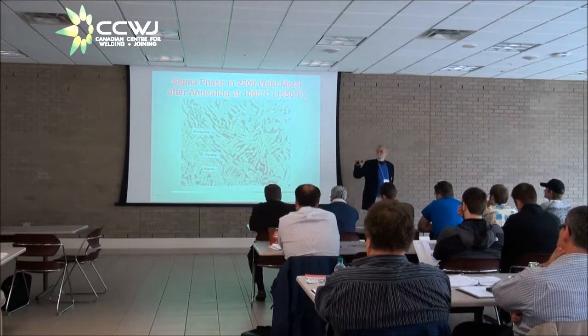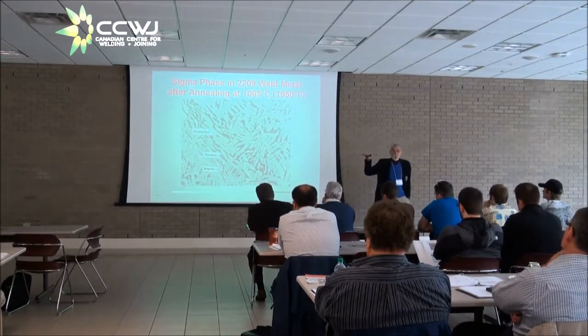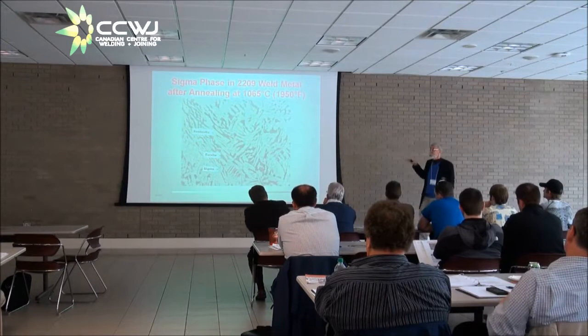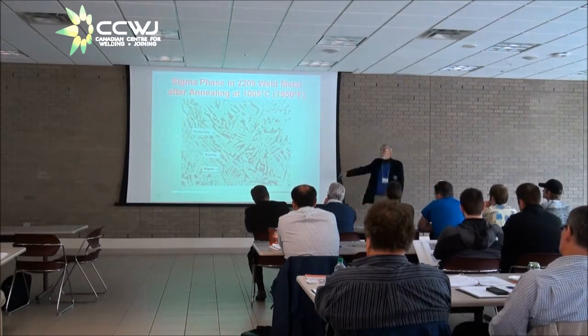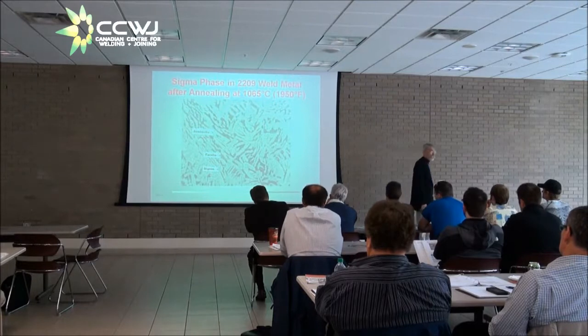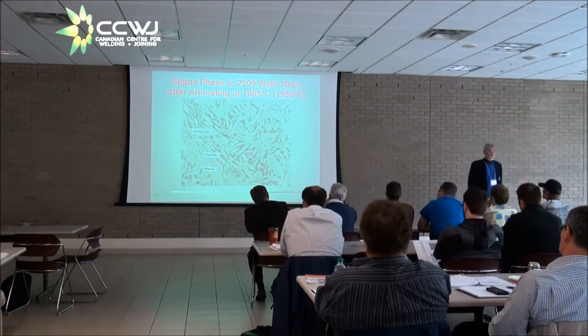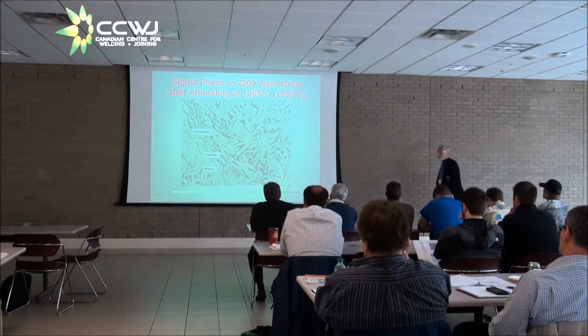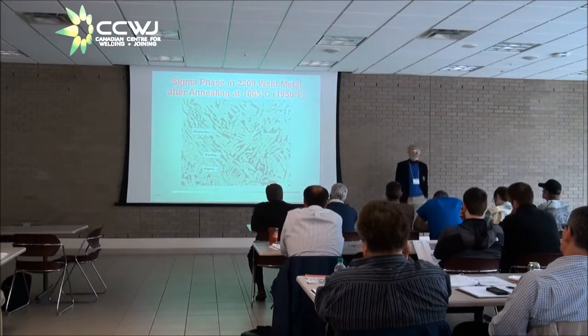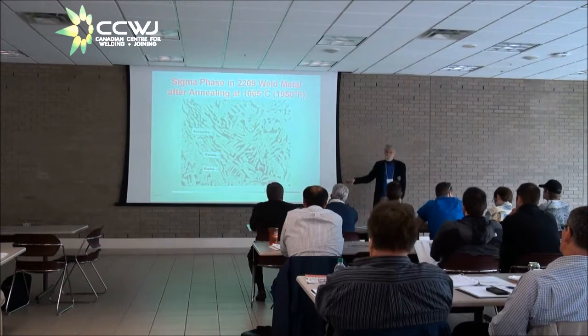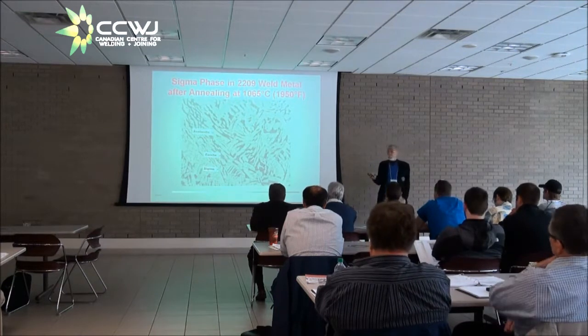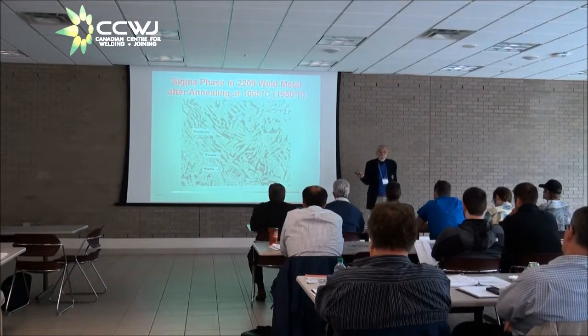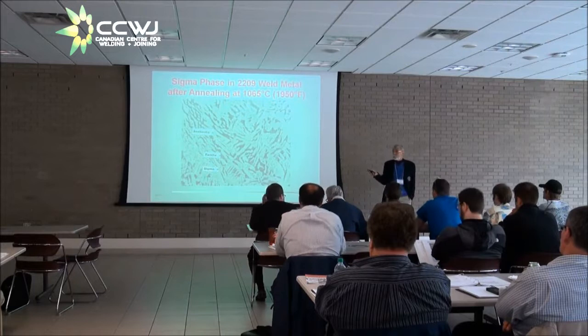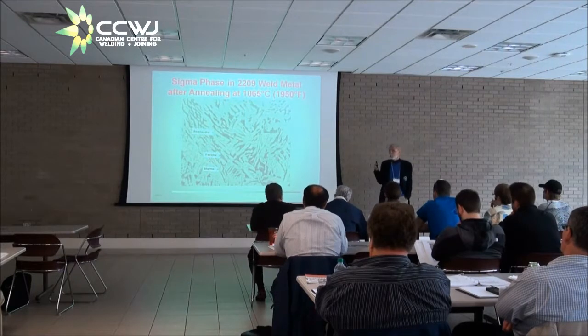So instead of 2 hours at 1065, I went to 72 hours at 1065. And I got exactly the same thing. It wasn't that I hadn't heated long enough to dissolve the sigma phase. It was that the sigma phase was stable at 1065. Then I took it up to 1100 degrees C, 1110. But anyway, after that anneal, I got good impacts, I got good ductility, and I measured the ferrite number again. And you know what? It was 45 again. The reaction was completely reversible. I could get the sigma to go back into solution, and I got ferrite.